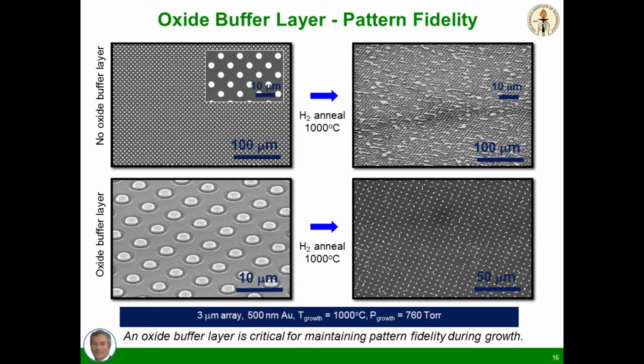crystallizes. Now, we tried this, and there have been 1,000 papers on growth of silicon nanowires, and all we got was felt. And we tried and tried for months, and that's all we got, and we rapidly then discovered the reason was that even though we laboriously patterned these metal dots on a silicon substrate in a perfect array by lithography, at growth temperature, after about 30 seconds, these balls all beaded up just like water droplets on your car, and that's called Ostwald ripening. And so if that's really the pattern on the right that we start with, it should be no surprise we get a variety of different diameters and directions of the silicon that is grown.